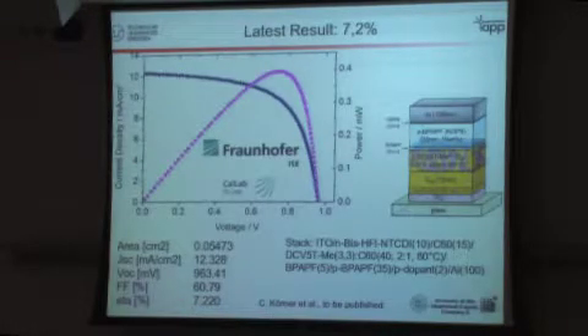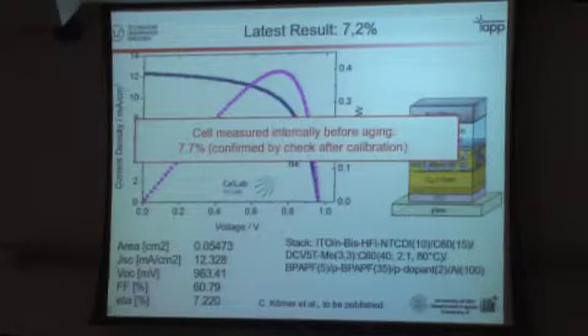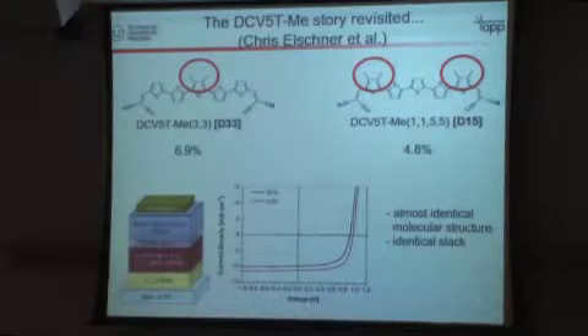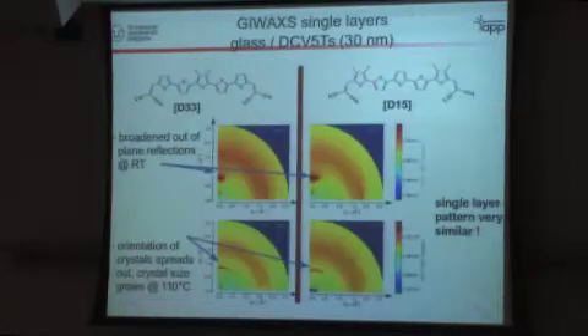In the meantime, we've done a little better. We reached over 7%, and in some internal results we are now at 8%, but still not really at the potential of the material. However, we have recently revisited that story. We processed the materials once more, and we confirmed the efficiency that compound 3 was better than compound 1. But then we looked in more detail at the structure.